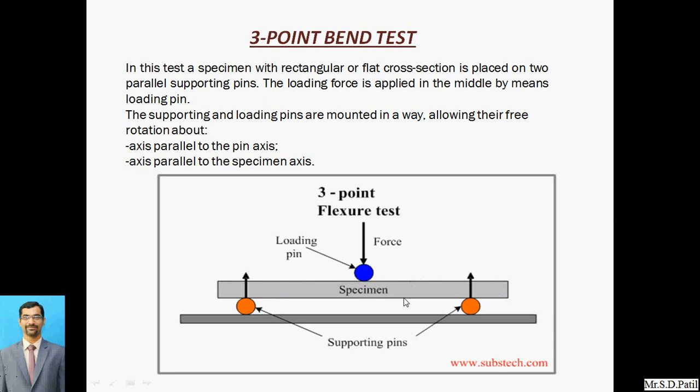There are a few specimens which are round also, but generally while manufacturing the specimen, considering the S to D ratio, normally it will be 16 for the majority of materials, and when we want to keep the shear stress on the lower side, we maintain that ratio from 32 to 64, the length to depth ratio.